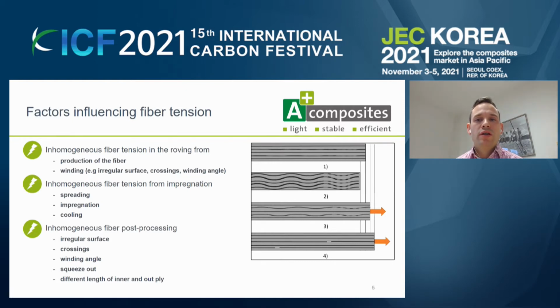And by cooling, this stage can be maintained and be frozen to post-processing. From our experience, the most critical point is the post-processing, because when you now have like 90 or 80% of fiber strands left, you can lose a lot of fiber strands, which I'll show you later on.